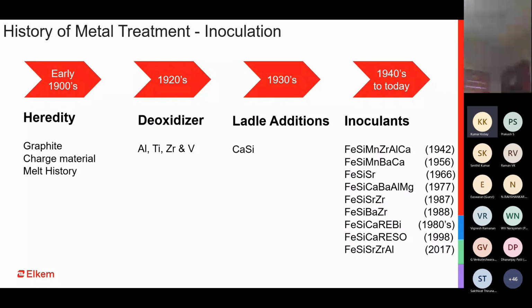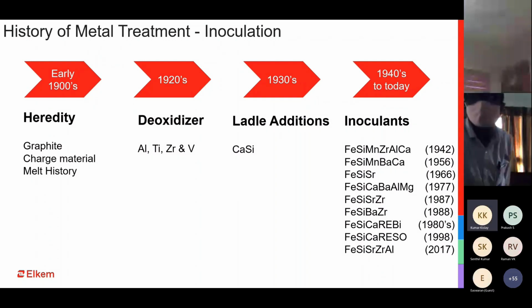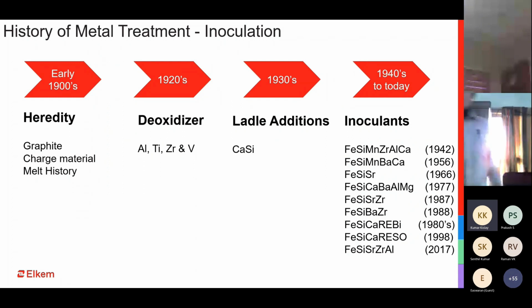I would say that strontium inoculants, especially Superseed grade inoculants, are probably the best inoculants that we have even today for gray cast irons. There was a short period of time when magnesium was also introduced into the system as an inoculant. The role of magnesium was quite contrary to that of calcium barium. When magnesium was introduced as an inoculant, it was not added to give you a graphitization effect. Magnesium was actually added to control the graphitization effect.